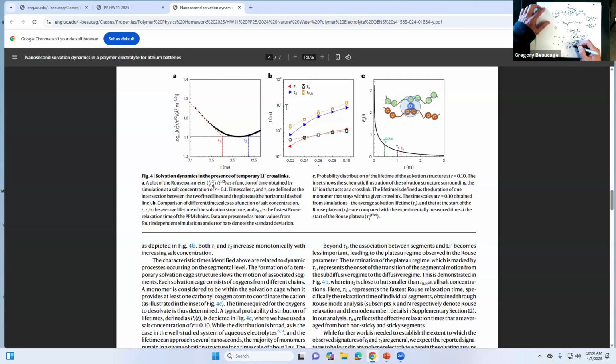You can study them in the same way. They can have the same kind of behavior, like a modal. If you have a guitar string, then it's got the first order mode and the second order mode, etc. And all the energy is kind of in that mode. That's the main thing you hear when you strum the guitar. But there are these other overtones that exist, at higher frequency. So this material is going to have the same. By the Rouse model, you end up with this idea: this first order Rouse mode, that tau_s is proportional to the molecular weight squared.